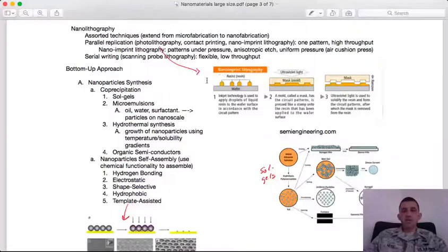Because the light is going to diffract through those really small spaces, but you can use it as an imprint mold. So instead of having a mask that light shines through, you have, say, deposited resin that is patterned by the mold. So you have contact between the mold and the resin. The resin fills the spaces in the mold, and the mold is transparent to ultraviolet light.